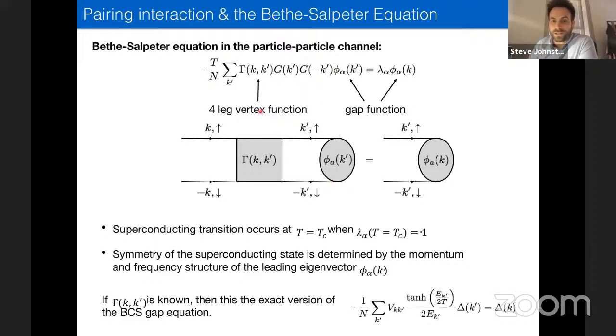Loosely speaking, you can think of this as a generalized BCS gap equation, where this is the general interaction between the Cooper pairs, and this is the eigenfunction which describes the structure of the Cooper pair. In this formulation, the superconducting transition occurs when the eigenvalue of this Bethe-Salpeter equation hits 1. That's when I take a Cooper pair, I interact, and I get back that Cooper pair again with no decay. The symmetry of the Cooper pair can be extracted by looking at the momentum structure of this. So the important point here is that we can put in the band structure, we can put in the U estimates that came from the DFT calculations, and we can unbiasedly calculate the leading pairing instability in the system.